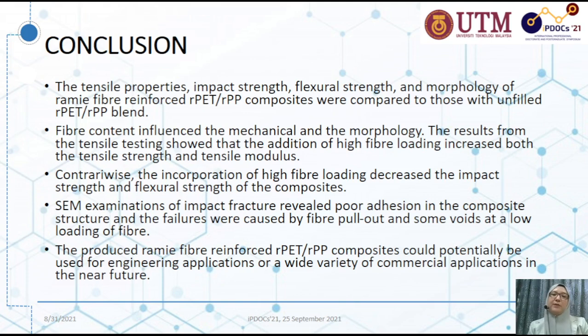From SEM examinations, the impact fracture revealed poor adhesion in the composite structure, and the failures were caused by fiber pull-out and some voids at the low loading of fiber. We can see here that the produced Rami fiber reinforced recycled PET, recycled PP composite could potentially be used for engineering applications for a wide variety of commercial applications in the near future.